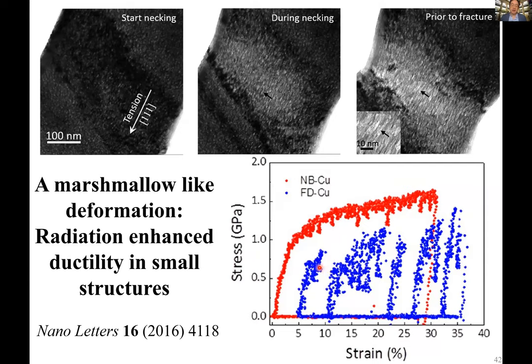Without the helium bubbles, there is this so-called size effect in the tensile stress-strain response. This is because when you have a dislocation, you generally have an avalanche that moves from one surface to the other, so you get a huge strain burst. But when we inject the bubbles, there is hardening, but we don't see this kind of flow serration, and it's actually pretty ductile. So this taught us that helium embrittlement is very closely related to grain boundaries.